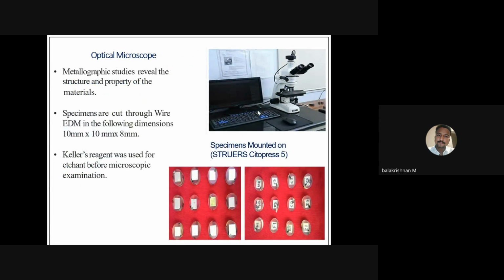Then optical microscope. In this, most of the researchers make this mistake. Actually, whenever they are preparing the sample, they are just preparing it without any mount. Nowadays, in most cases we are using a mount. The mount is very useful to hold the component in a parallel way to get a more clear surface. And Keller's reagent was used as an etchant for this.